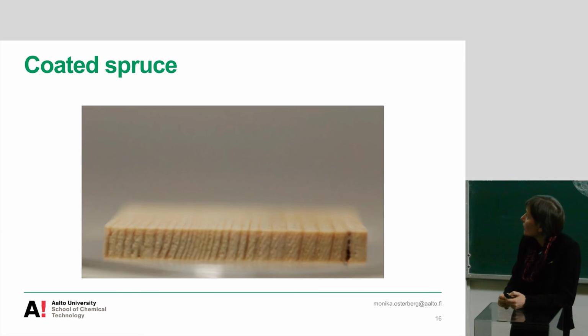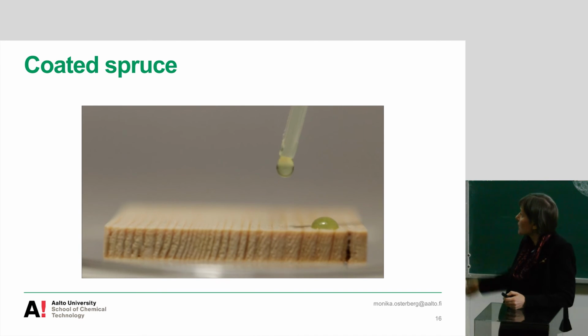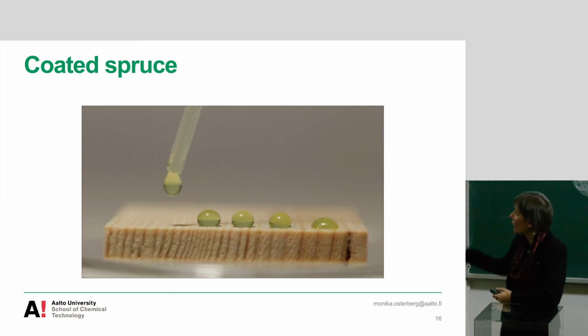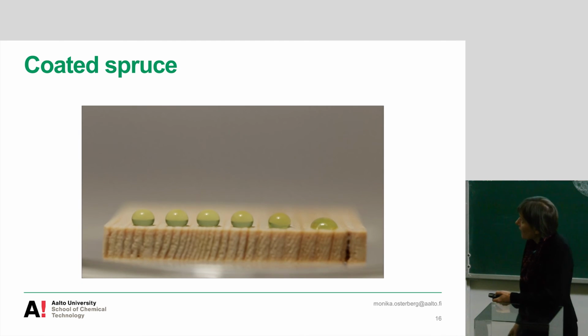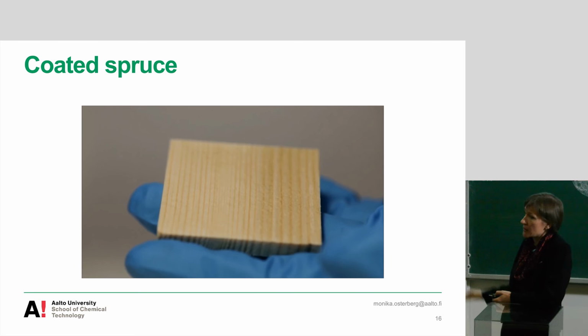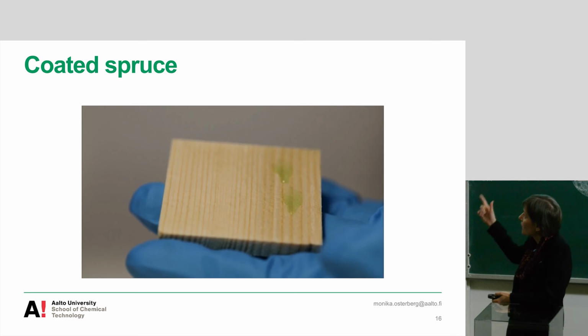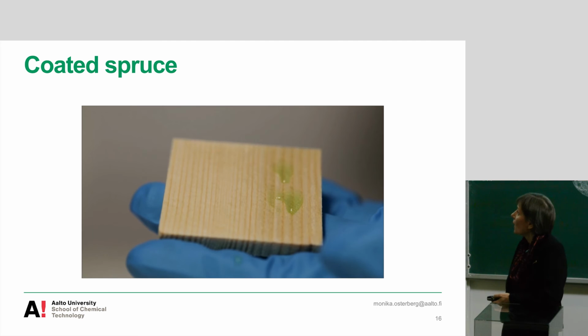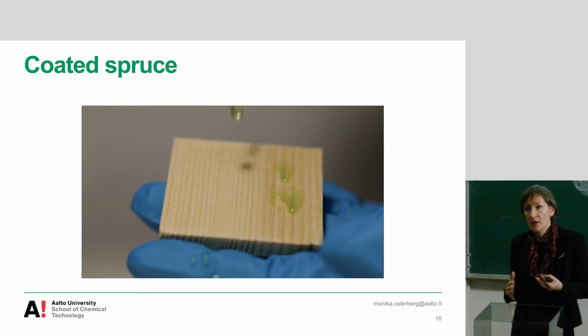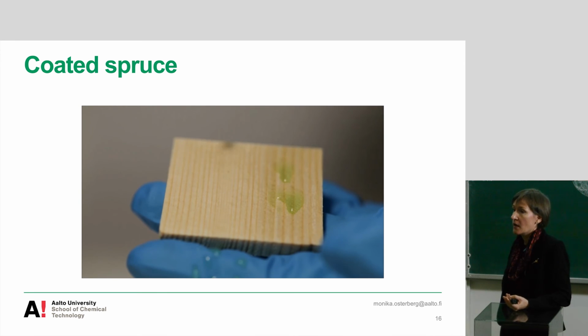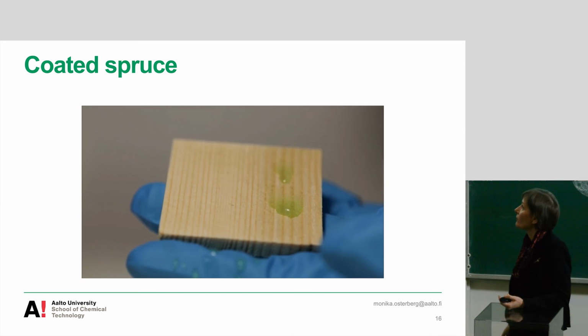So here's a video of the modified wood. So you see that's the unmodified part where the water spreads a bit, and then on the modified part it forms quite nice droplets. And if we look at how it rolls, we can see that on the unmodified one the water sticks, while on the modified one the water quickly rolls off. So we can think that if we have walls of this material in the bathroom, for example, the water will very quickly roll off and then it can dry out.